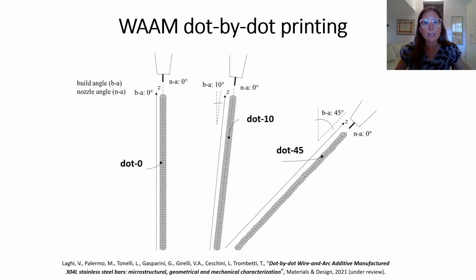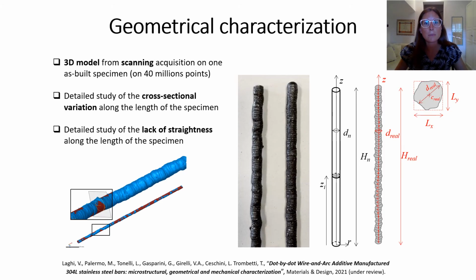The experimental investigation was carried out on WAAM-produced stainless steel bars realized at 3 different build angles: at 0 degrees, so with the same direction as the vertical gravity axis, at 10 degrees, and at 45 degrees. The aim is to evaluate the possible influence of the different build angles on the mechanical response. The first part of the experiments was devoted to characterizing the geometry of the printed rods from 3D scan acquisition. The geometrical irregularities were assessed in terms of lack of straightness and diameter variability.